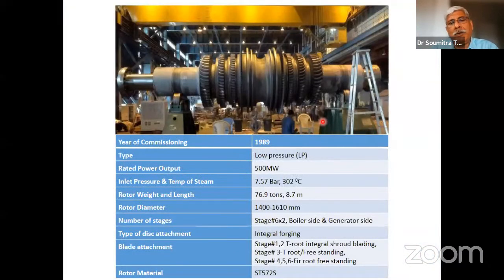So this is the rotor we are talking about. It's a huge rotor, 76.9 tons, 8.7 meters long. It was part of a 500 megawatt system, which operated at 302 degrees centigrade. 6 stages, 6 into 2 on both sides, boiler side and the generator side. And one of the stages, the 4th stage on one side, during inspection, during a shutdown, was found to contain a defect. And there were, of course, telltale signs of vibrations, of problems with its bearings, etc., which told the people who were operating it that they could not operate this. And this was lying idle.